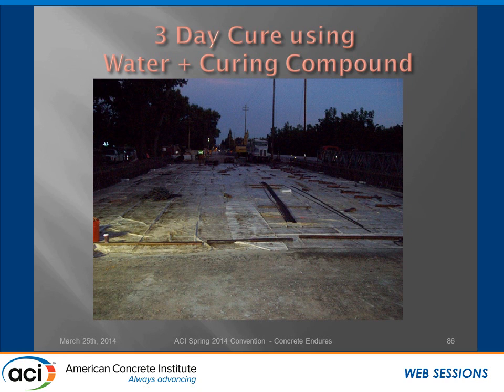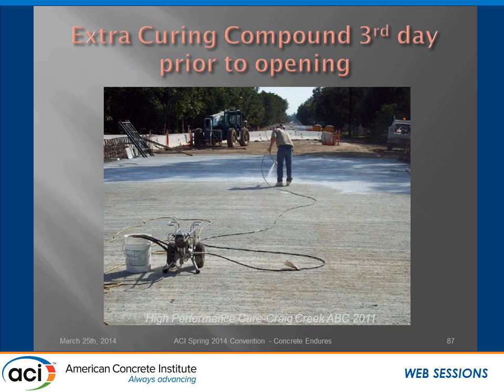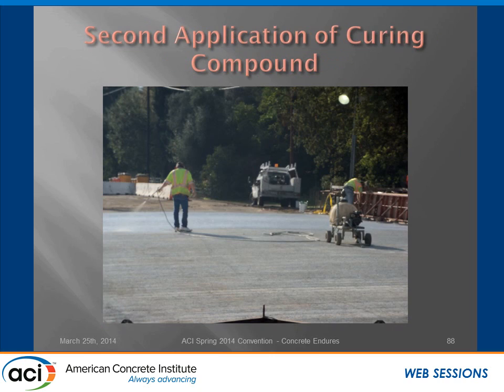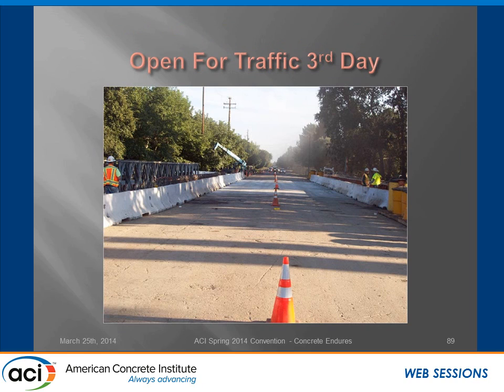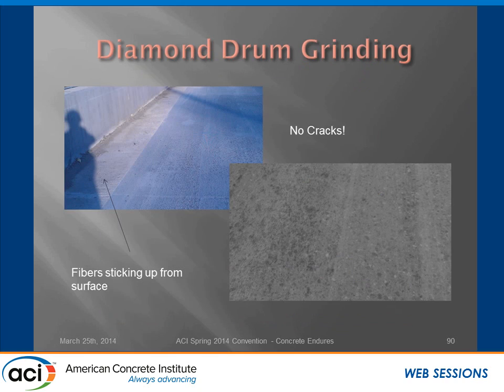Again, here's our third day of water cure and curing compound. We open her back up to traffic, put some more pigmented cure down, let it get set up so it doesn't get picked up by the traffic wheel loads, and then we open up to traffic. And like I said earlier, we did all this in an accelerated bridge construction fashion, and we really didn't have any cracks. 7 weeks later, we went back and ground the surface of that concrete off with a diamond grinder so we could see whether we had any cracks or not, and we didn't have any cracks.